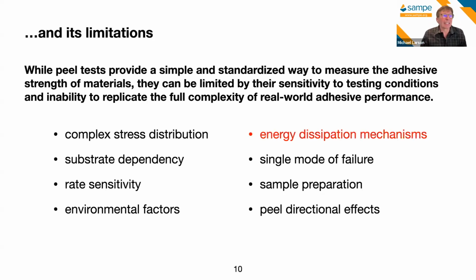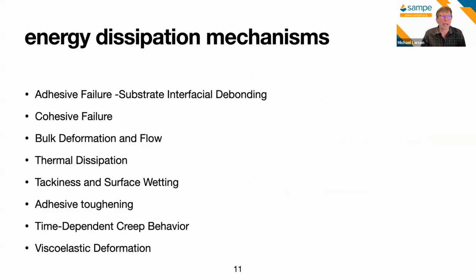The one, though, that really rears its head when we think about pressure-sensitive adhesives is this energy dissipation mechanism, which is what makes this class so valuable, but I would say why it's so difficult to accurately model. And what we find here at work in these PSAs that are holding two surfaces together, we can have adhesive failures where we see interfacial debonding, the adhesive separating from the surface.